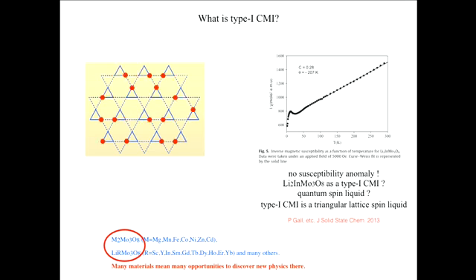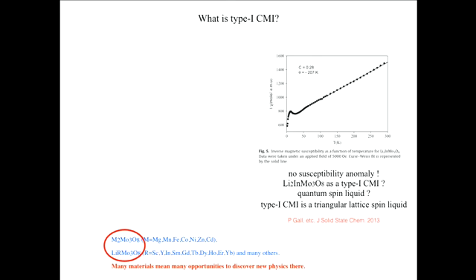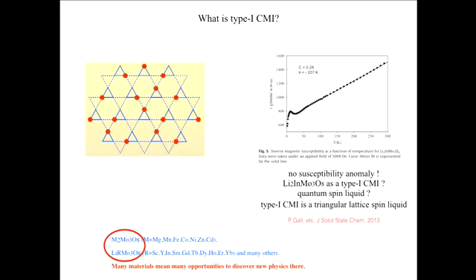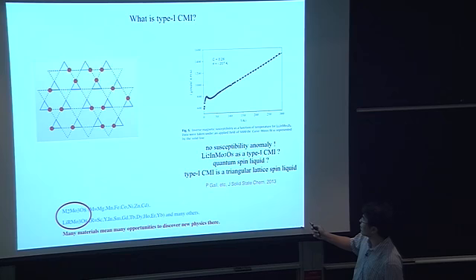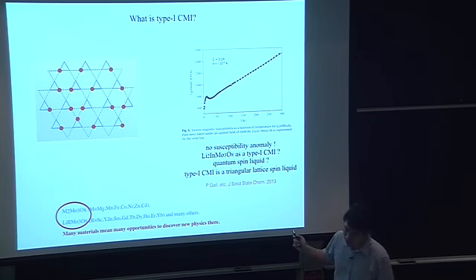So in this material, lithium indium molybdenum oxide, there is no spin susceptibility anomaly, and at very low temperature, the spin susceptibility almost becomes a constant. At very low temperature, there is a sharp peak due to impurity. So that's actually compatible with this material being a type 1 cluster Mott insulator. But there is very limited experiment. I can't tell you too much about this.